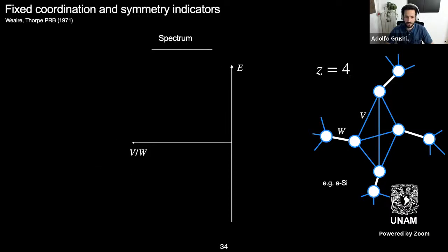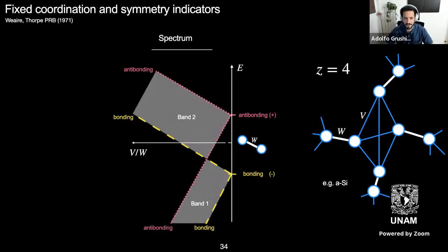Now you don't have bands, so you cannot use K. So what you do is you plot it as a function of these two parameters. And if V is strictly 0, what you have is just these W bonds, and this will just be dimers. So you will have many dimers kind of randomly oriented in space. And you know that a dimer has 2 states, a bonding and anti-bonding state. And these will be very degenerate, so much as the number of dimers in your system. And now as you tune V, you will start lifting this degeneracy, and you form these bands. So this is the gray area here.